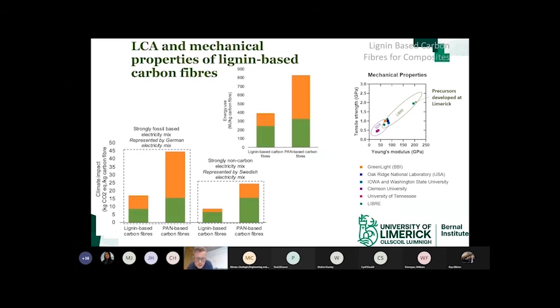This is some of the LCA results. You can see that there's obviously great benefits with regards to energy and carbon emissions. And the key development here is our mechanical properties. The state of the art is down here at 1 gigapascal tensile strength and about 100 gigapascal modulus. Our materials developed here in Limerick are up here at 2 gigapascal, so twice the state of the art in terms of strength and stiffness.